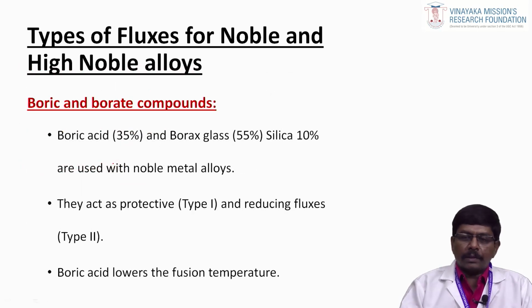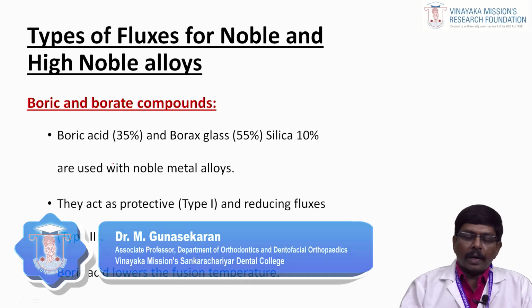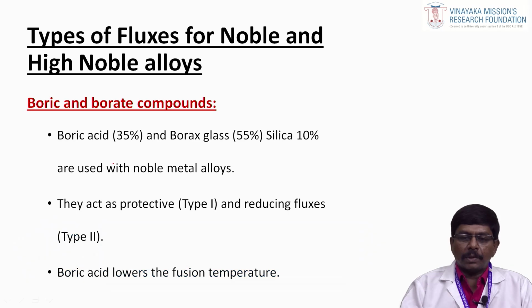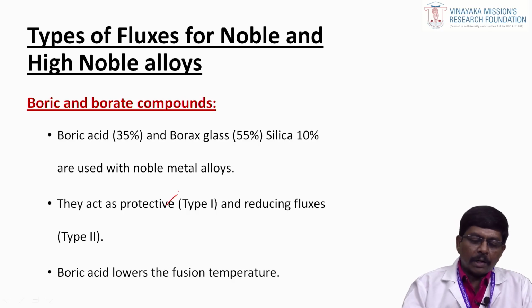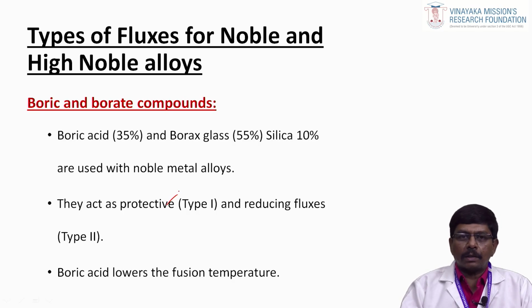Coming to fluxes for noble and high noble alloys, boric and borate compounds are used. Boric acid 35%, borax 55%, silica content is 10%. These three are used for noble metal alloys. They act as type 1 protective fluxes as well as reducing fluxes, that is type 2. Here the boric acid lowers the fusion temperature of the alloy.